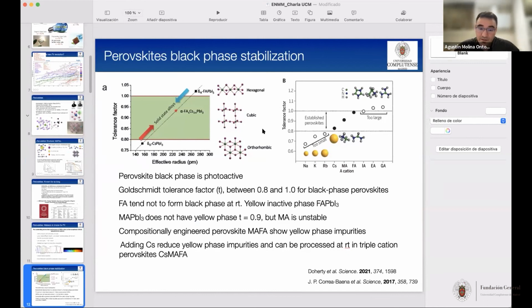Then about the research of a lot of people doing these kinds of perovskites, we started with this methylammonium. Then the mixed cation, mixed anion seems to be even more stable than the other one, because now we have formamidinium in the structure, so it's not so easy for methylammonium to leave the structure. And then just by adding cesium, we have the triple cation perovskite, which is much more stable, as we saw in our case.